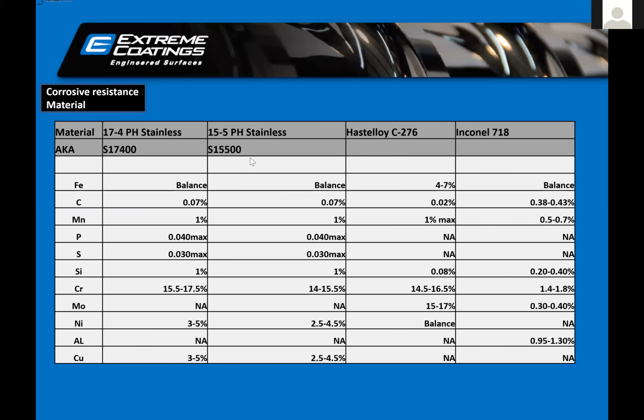Then there are corrosion resistant materials, as I spoke. If you see all these steels, the chromium percentage is very high. That's what makes them more corrosion resistant steels. The limitation of these steels is that they are not good with abrasive or adhesive wear, because they do not have a high percentage of molybdenum, they do not have any tungsten inside, they do not have any vanadium inside.